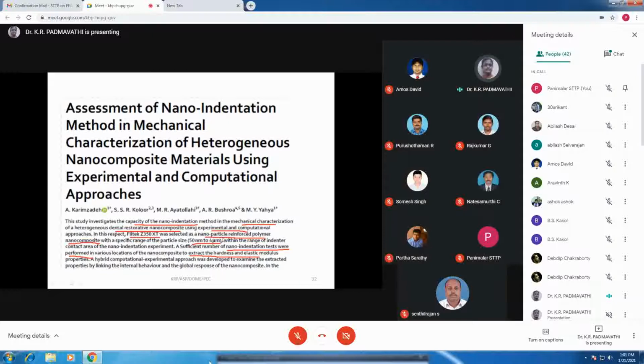Okay, they have selected Filtek Z350 XT as their workpiece material, a nanoparticle reinforced polymer with a specific particle size of 50 nanometers to 4 micrometers. So within the range of the indenter contact area of the nano indentation experiment, a sufficient number of nano indentation tests were performed at various locations of the nanocomposites to extract the hardness and elastic modulus with the help of the loading and unloading, load displacement curve, from which they have got